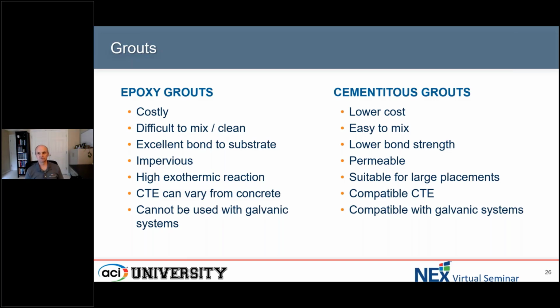in terms of the material itself, and also in terms of placement, just because epoxies are a lot more difficult to mix and apply. They require special equipment. The equipment has to be cleaned frequently because of the nature of the material that you're dealing with. Also, epoxy grouts can have very high exothermic reactions, which means if you have a very large annular space between the jacket and the existing structure, if you're trying to encapsulate something that's, say, 0.5 meter thick, that high exothermic reaction is potentially going to cause issues with cracking of the grout, just because of the sheer mass of grout that you're trying to place.